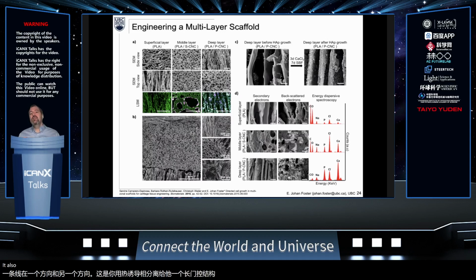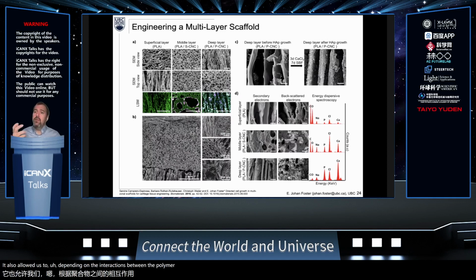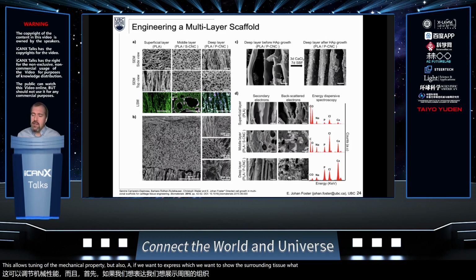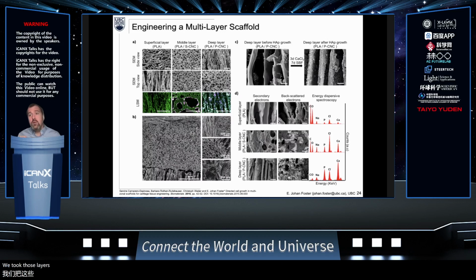It also allowed us to, depending on the interactions between the polymer, the solvent, and the cellulose nanocrystals, have the cellulose nanocrystals present at the surface of the material or embedded within the walls of the material. This allows tuning of the mechanical properties, but also if we want to show the surrounding tissue what that surface chemistry is, we can do it. We took those layers, we fused them together.